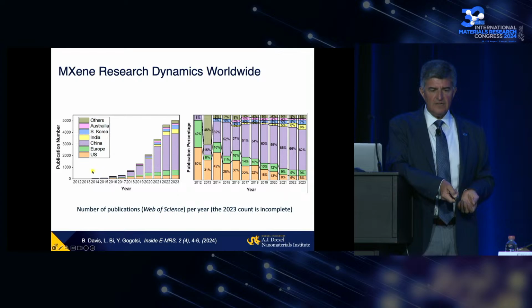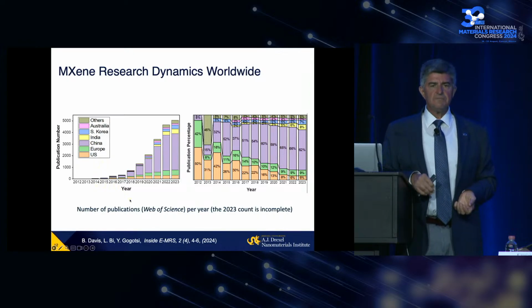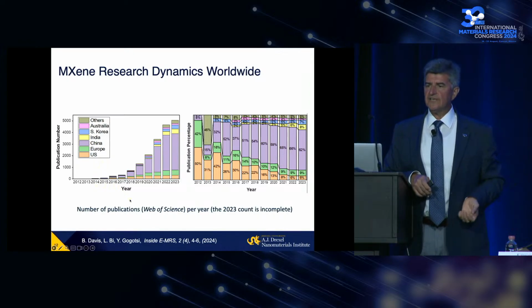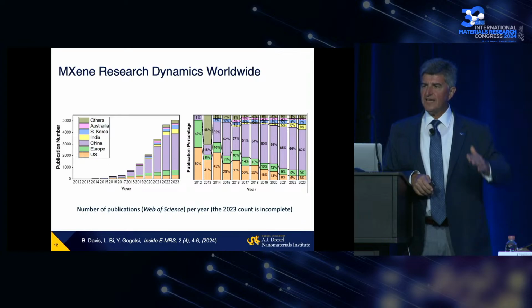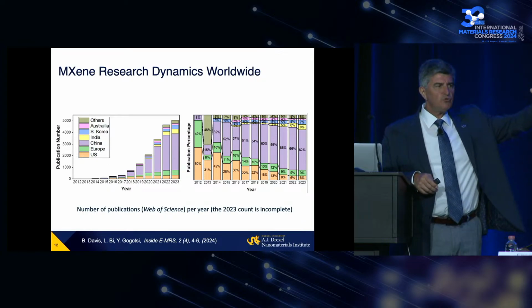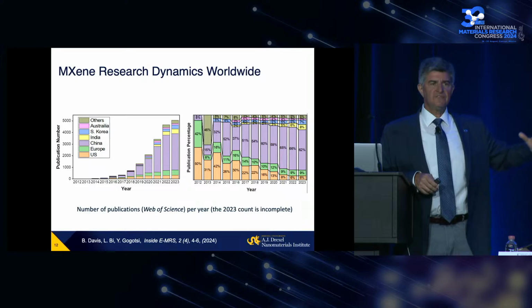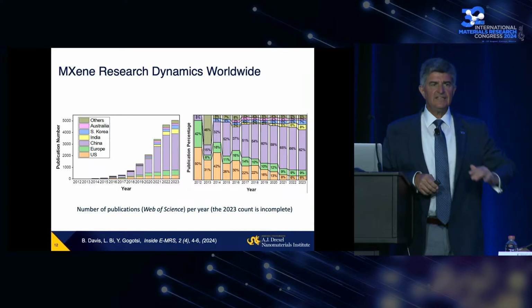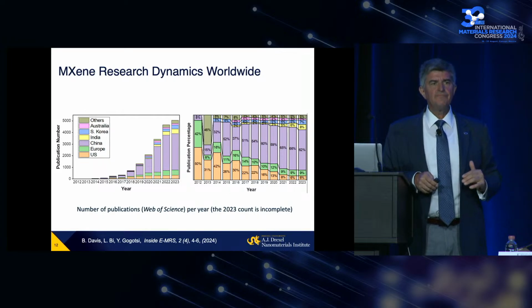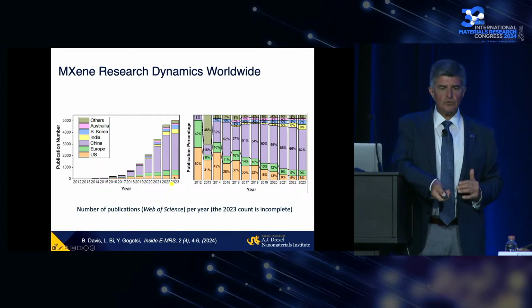You can see, in the first few years, there was very little interest in this family of materials. In 2016, when we showed that MXene outperformed all other materials in electromagnetic interference shielding, they started getting into pretty much every field of application where people have been using graphene and other 2D materials, showing the best results ever. This is where the interest started to grow and increase.